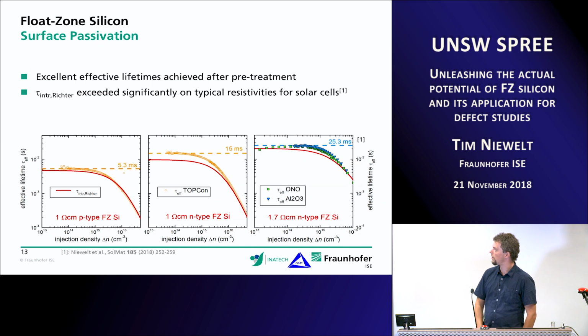Some further results on that. So here with the injection dependence, because these are something like notable exceptions that we've seen. So we get really good lifetimes, and we even get lifetimes that are better than the widely used Richter model for Auger recombination. So the effective lifetimes that we're measuring here are actually way higher than the theoretical limit predicts the lifetimes for float zone silicon to be. So the Richter limit is exceeded significantly on these samples of typical resistivities for solar cells. So I mean, the range of 1 to 2 ohm centimeters is actually where a lot of solar cells are being done. So this is also the doping range that's very relevant for modeling solar cell efficiencies, for example.